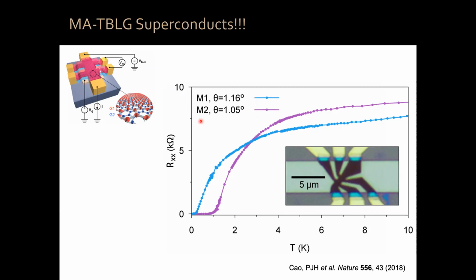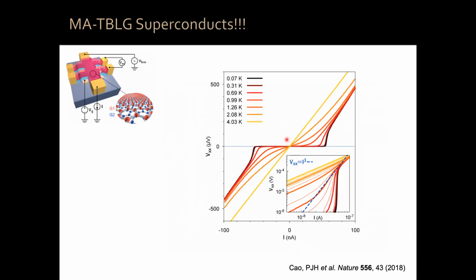Okay, now you can look at any measure of a 2-dimensional superconductivity that you want. For example, you can measure the VI curves. You see, you can run a current through magic angle graphene without any voltage dissipation, until the critical current. This is perfectly 2-dimensional superconductivity.